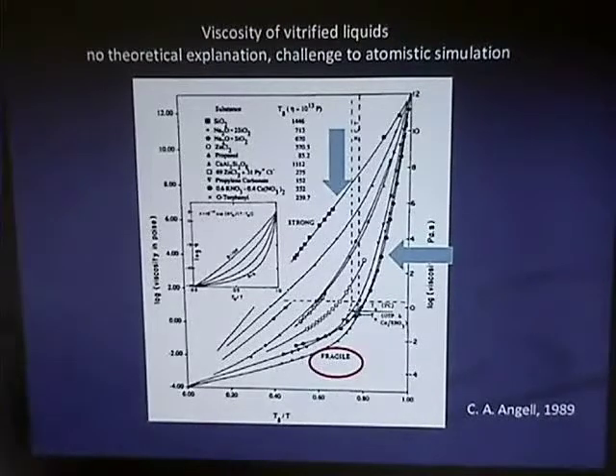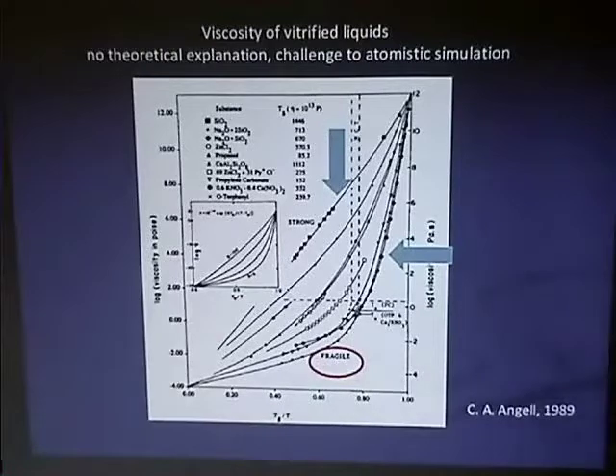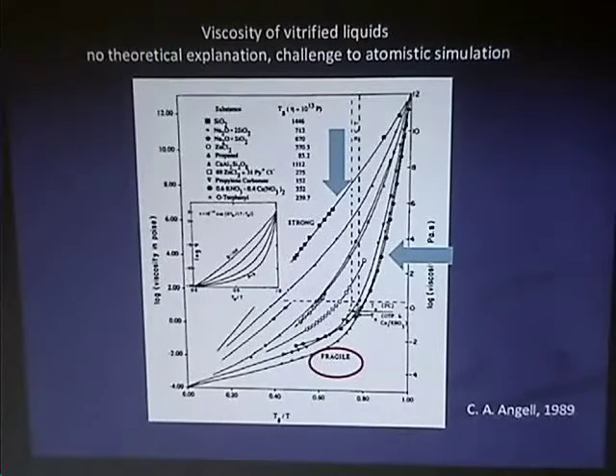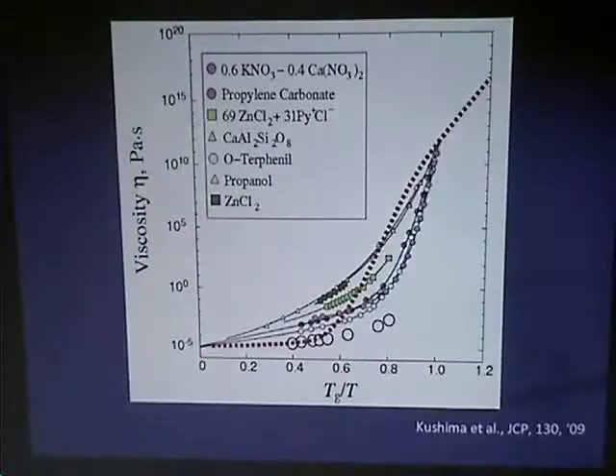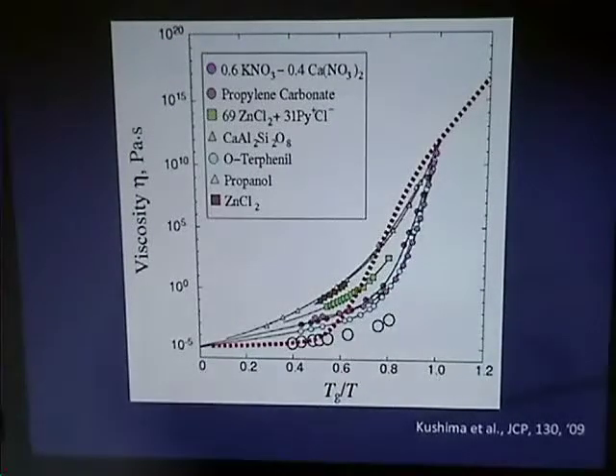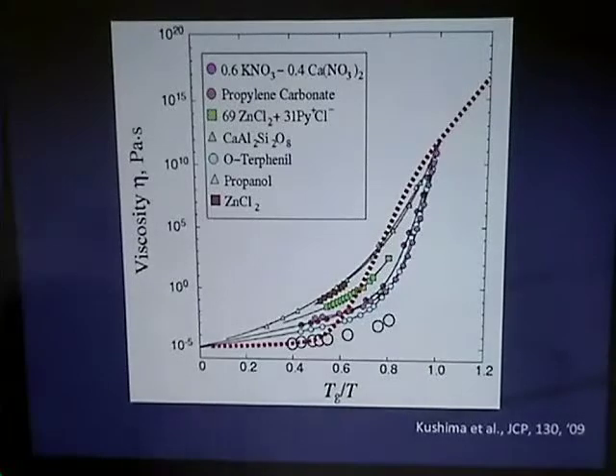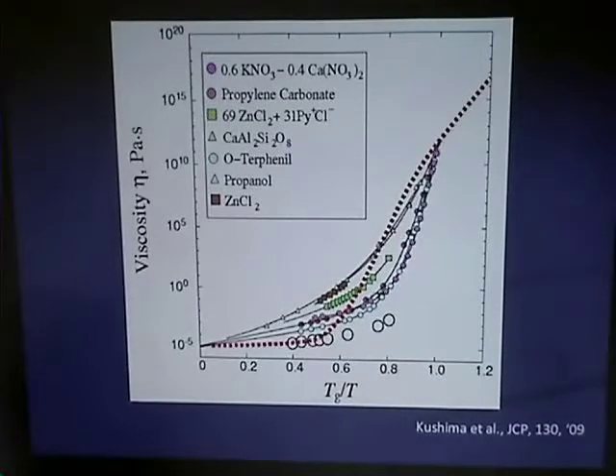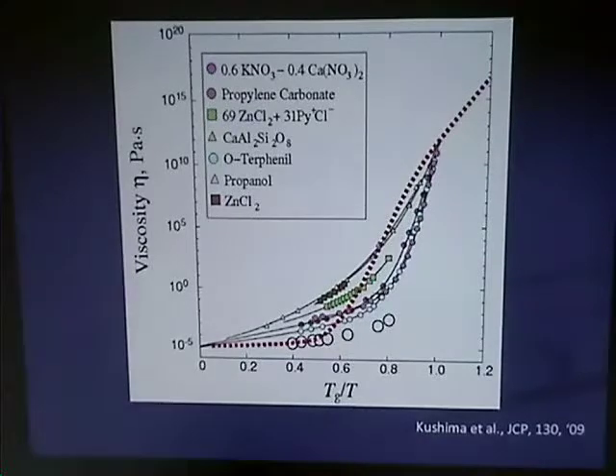Anyway, let me just show you the problem. One of the things worth noting is if you go beyond TG, the temperature dependence apparently changes. Beyond which TG? Well, you say where there's a maximum in your specific heat. Well, that's not the same as 10 to the 12 poise - for small molecules it's not that far off, but it's not the same thing. In that vicinity though, the main point is there's a change in character.